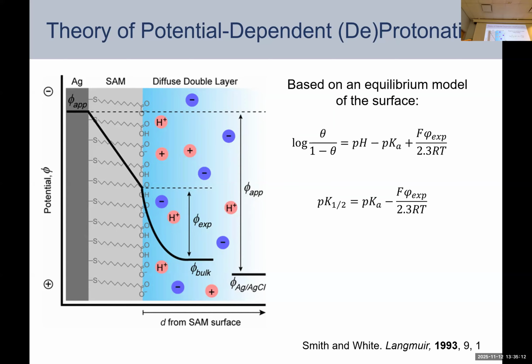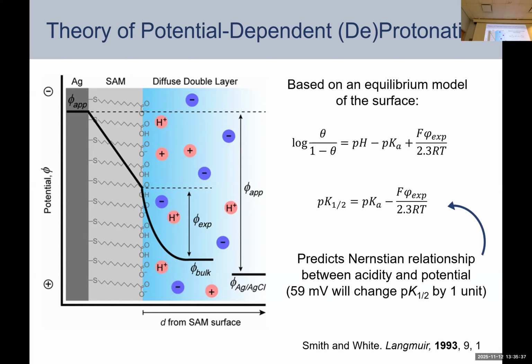And you might think, okay, well, let's write out an equilibrium model of the surface here. And we're not going to go into all the derivation here, but we can define a term here, pK1/2. This is like a pKa, but it's the solution pH at which half of your molecules on the surface are protonated and half are deprotonated. And that should depend on the potential here in a sort of Nernstian relationship.